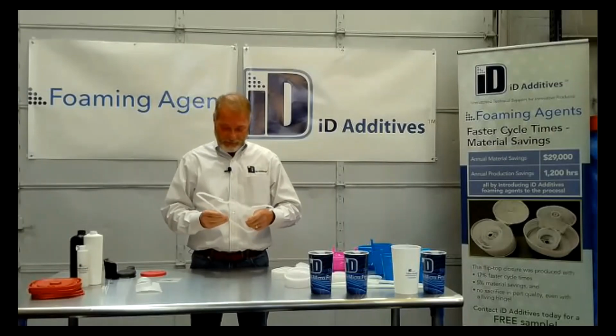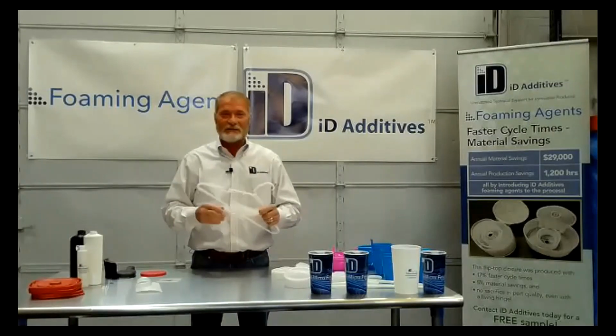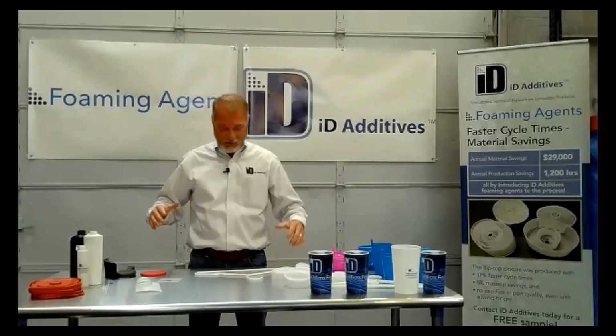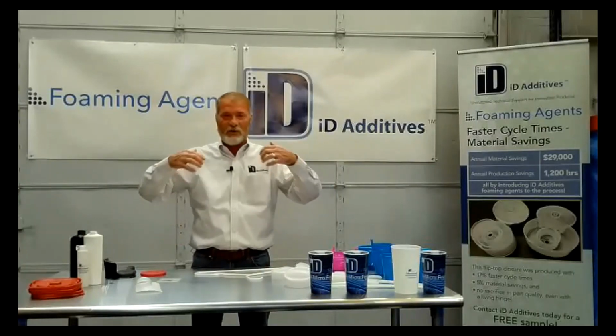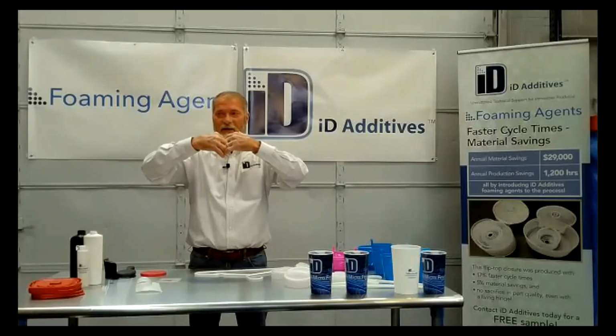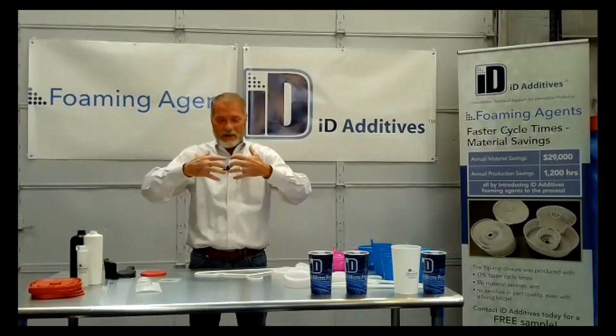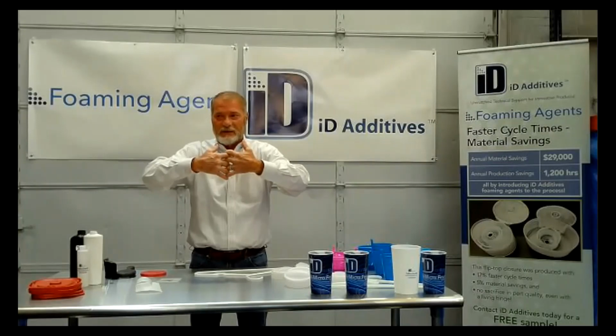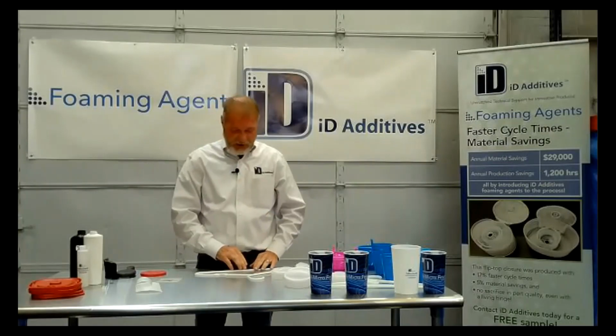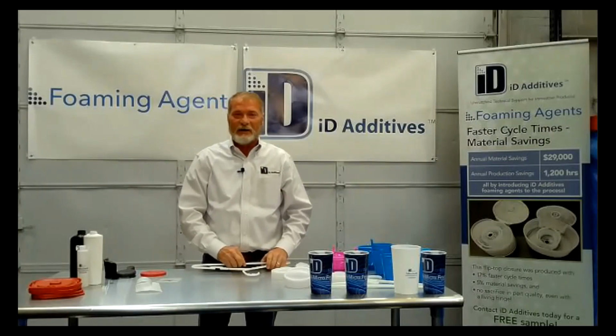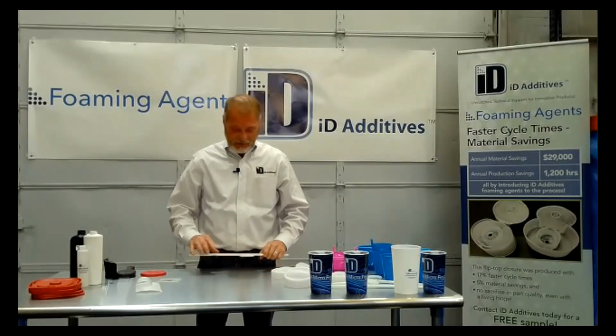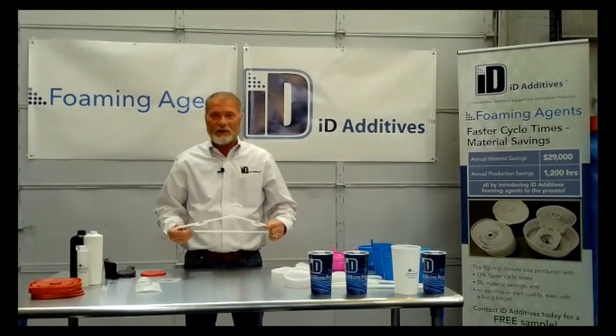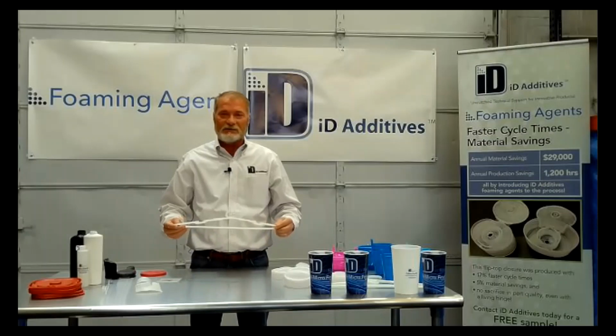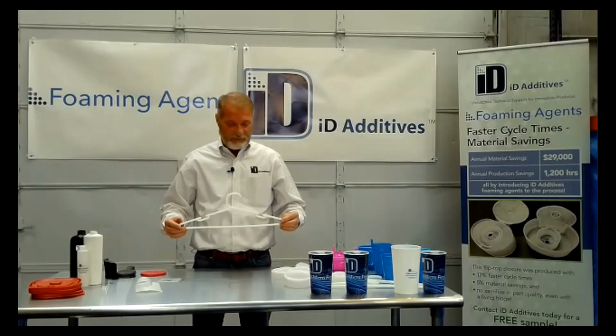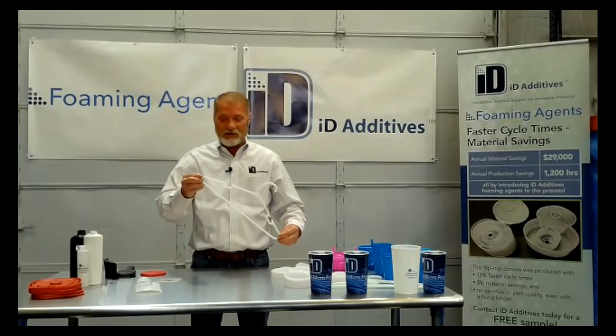Well, with the foaming agent, because it flows, you've got two cold fronts of no foam at all, they'll come in about like that. But when you add foam, it'll actually go a little bit further, and it'll lock in a little tighter. So your knit line right here tends to be a lot stronger. There's no voids in the part. Weight is achieved, and it's just solid all the way through.